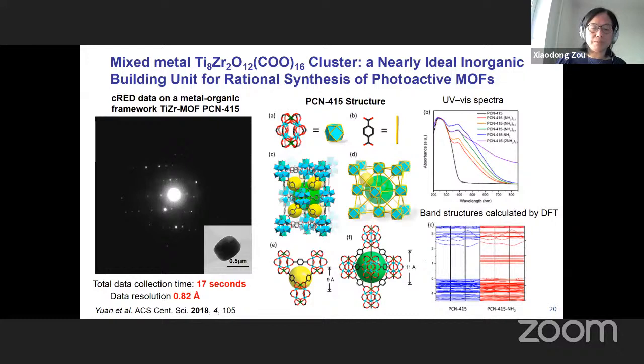And you can also play with the metal clusters. In this case, you have mixed metal clusters, titanium and zirconium, and this data was collected in a very short time, only 17 seconds, from a 500 nanometer sized crystal. And this is enough to get the structure. The structure was built by a cluster, and this cluster contains both zirconium and titanium, like this kind of cluster. And the organic linker is like this here, and you can also tune the organic linkers.